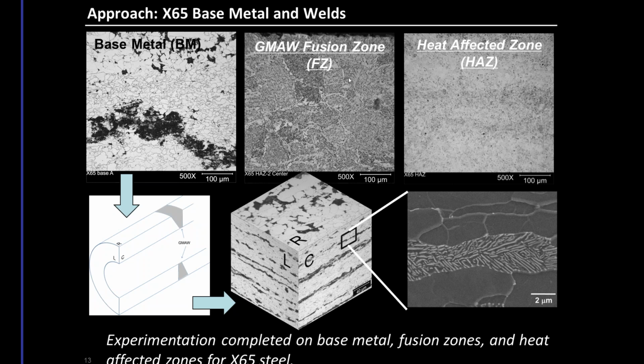The weld microstructure itself was distinctly different from a ferrite pearlite. It was various morphologies of ferrite, including grain boundary ferrite, allotriomorphic, and some Widmanstätten ferrite, as well as some dispersed carbides. But it was a refined microstructure as compared to the base metal. And then the heat affected zone microstructure really appeared to be like an annealed base metal, an annealed ferrite pearlite, which is really what had happened, because as the welding process heats up, that heat is absorbed into the surrounding material, and it affects the microstructure around it. So this was the first set of microstructures we looked at.